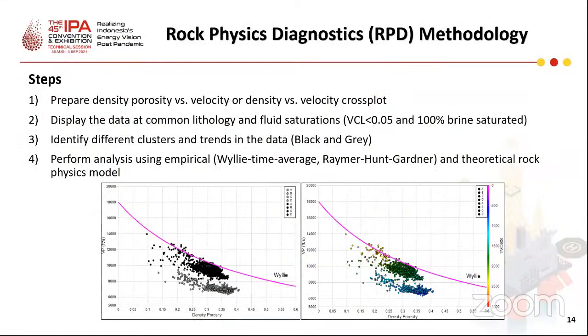Here we discuss the rock physics diagnostics methodology. The key steps are as below. First, we prepare a crossplot between density porosity versus velocity, or simply density versus velocity crossplot. The density porosity has been computed using rho matrix as 2.65 and density of water as 1 gram per cc. This is because we are analyzing the data just for the clean formation with volume of clay less than 5% and 100% brine saturated data points.